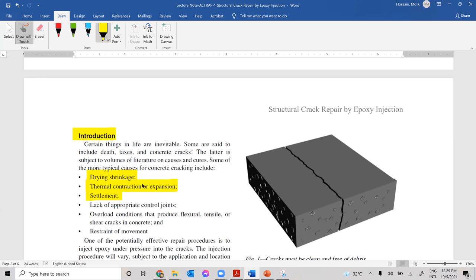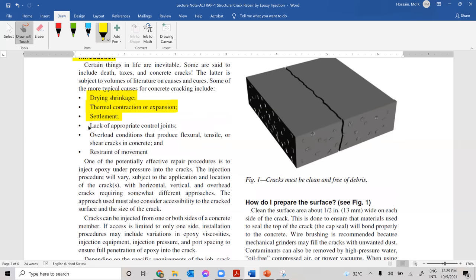Some reasons why concrete cracks include drying shrinkage, thermal contraction or expansion, and uneven settlement. When concrete hardens and sets, it releases surface water. Due to the fast rate of surface water release, the top surface tries to contract. Since concrete is weak in tension, it develops cracks because it cannot take the tensile stresses.